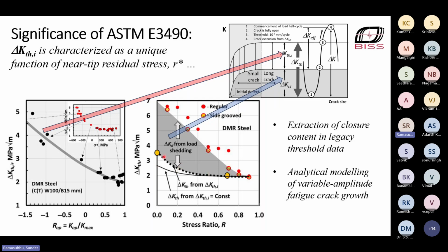So what this implies is that when a crack is growing naturally, this is going to be the curve it will follow. This is the property it will follow as a function of applied stress ratio. So the new standard actually helps you get more realistic, or treat it as conservative, values than what you would get using prevailing methods. And once you get the intrinsic threshold, if you have legacy data, there are hundreds of data points available from previous experiments. From those, knowing this relationship, you can extract what was the closure component. At least you will find out how wrong we were in determining it the old way.